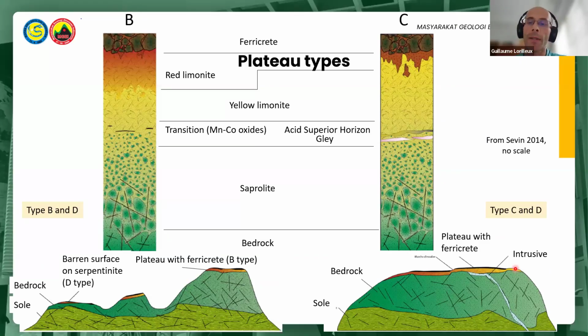Plateau deposits are located in elevated areas where the internal drainage is free. The water table is low, and leaching and precipitation are optimal. Plateau deposits can be truncated with less ferricrete and limonite due to erosion in lower altitude on mountain sides. They are characterized by a well-developed saprolitic horizon due to high drainage. The C-type in Sevin's classification on the right here is characterized by the abundance of smectite and an aluminum-rich bedrock, for example, due to the presence of lherzolite, feldspar-rich intrusive, or gabbro-cumulate and wehrlite.